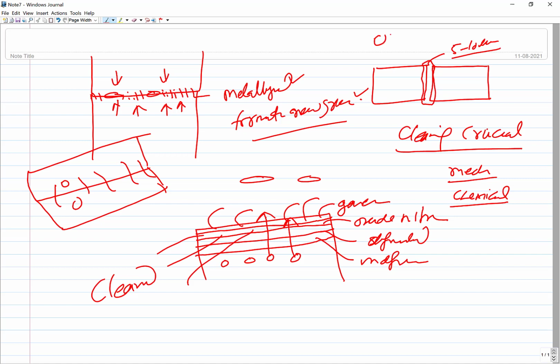This is typical of ultrasonic welding or explosion welding. But if the deformation is taking place in the underlying metal, how is it going to help you in joining? No way, because it is not useful in any way. If the base metal is getting deformed or the HAZ is getting deformed, how is it useful in joining? It's not. The deformation is crucial only to facilitate the interfacial metallic intimacy, so that diffusion across the interface can take place to develop a metallurgical joint. Deformation of the underlying metals on both sides is of no use.